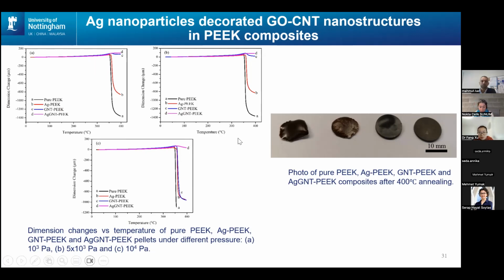To better study the thermal stability of the composites, we used TMA to study how well they keep their shape at high temperature with loading. With loading increasing, at 1000 Pascal, samples A and B lose their shape, meaning they've melted, while C and D keep their shape. At 5000, C has slightly lost its shape, meaning slight melting. At 10,000, samples A, B, and C have all melted, but D, the silver coated graphene nanotubes, still keeps its shape, showing very good thermal durability.